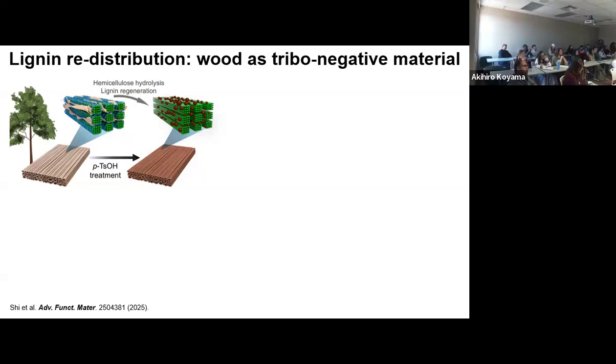What we did here was to take wood and dissolve in situ the lignin that exists in the cell wall and in the lamella between the fibers, right? And we use a special solvent. And what we observe here is that the lignin is dissolved, but we didn't make any effort to extract that lignin. We keep that lignin. And the observation that was made almost by accident is that the lignin that is dissolved finds each other and clusters into particles when we remove the solvent, water. It clusters. Again, add water, remove water. And then those clusters of lignin also migrate from the inner parts of the cells to the outside. So you have migration of lignin to the surfaces, and we have clustering.